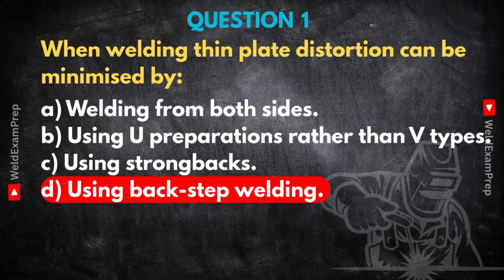They hold things in place and are often used alongside welding. But they can also introduce stress, which might cause problems later. And if they're too rigid on thin plate, you could even risk cracking. For thin materials, that localized controlled cooling from backstep often does a better job of preventing that initial buckling or warping right as it happens. It's like investing a bit more technique up front often saves a lot of hassle trying to fix a warped part later. Makes sense. So the insight is really about managing the cooling locally, preventing that continuous shrinkage front. For inspectors, it's a good reminder that sometimes the slower, more broken up approach is actually the most effective for quality.